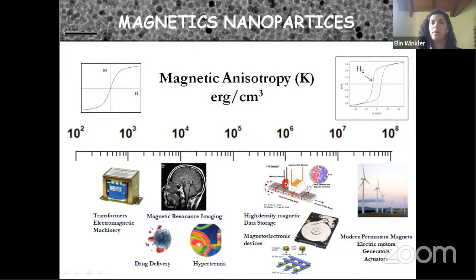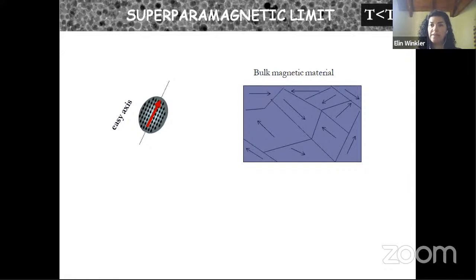So what happens when we have a magnetic material? Below the transition temperature, for example, if we have a ferromagnetic material below the Curie temperature, the spins are ordered inside the material, but in order to lower the magnetostatic energy, different domains are formed inside the material. Here I am drawing several sketched domains. In each one of these domains, all the spins are oriented along one direction. And this corresponds to domain walls. The creation of a domain wall has an energetic cost.